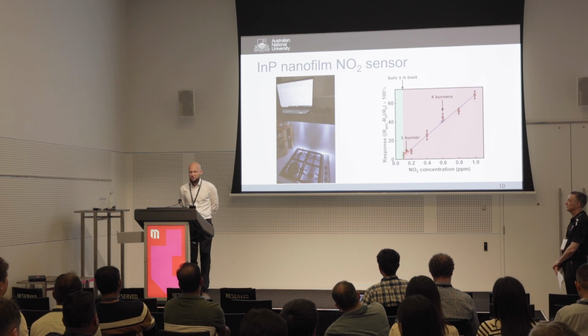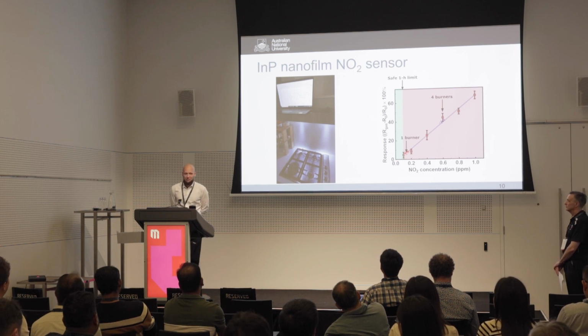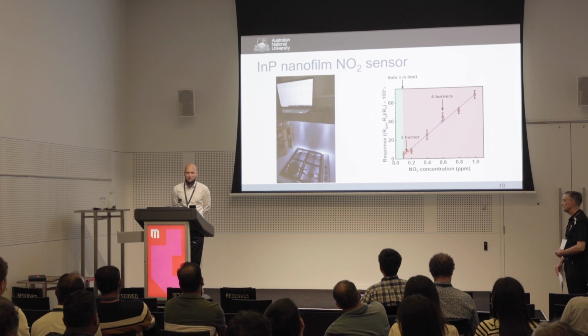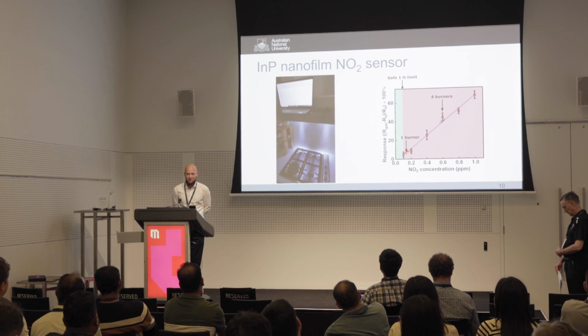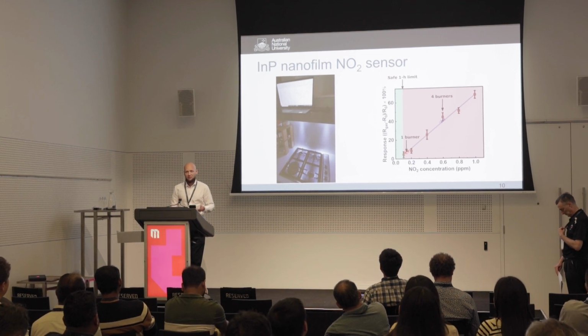And then on the temperature dependence, there is indeed a temperature dependence of these sensors. If you have higher temperature, then the resistance will decrease, so it's the opposite effect of the NO2 exposure. However, in a real or commercial practical device, we could have one sensor which is encapsulated and one which is exposed to the gas, and then we can track all of these environmental changes or differences.